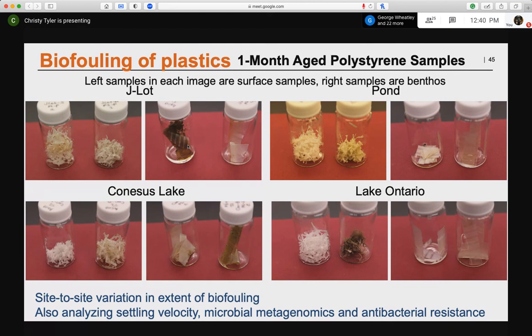In addition to this, we're looking at the settling velocities, how the settling velocity changes after aging, as well as the microbial metagenomics of the biofilm formed, and also the antibacterial resistance of the bacteria formed on these different samples. This is looking at it after 1 month. You can see differences in particle versus swatch, but also in terms of different locations and surface versus benthos.